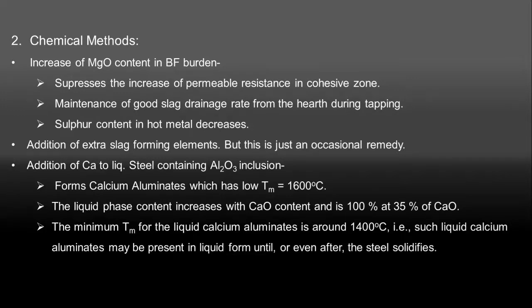Alumina inclusions in liquid steel are present in solid state. To convert them into liquid state, we can add calcium to liquid steel as it forms calcium aluminates with those inclusions, which have low melting point as low as 1600 degrees centigrade. Liquid phase content increases with lime. For 100% liquid phase, 35% lime is enough. The minimum melting point of calcium aluminates is 1400 degrees centigrade, that is, they will be in liquid state even after steel solidifies, or at least until steel solidifies.